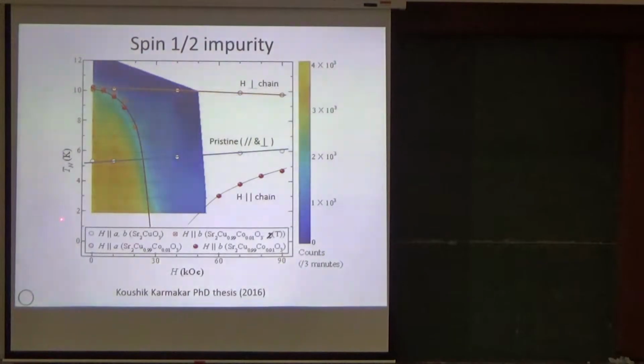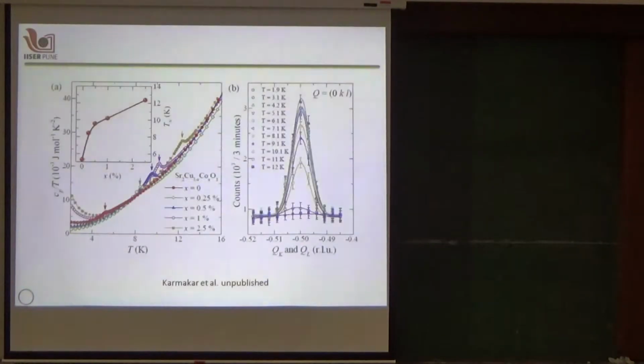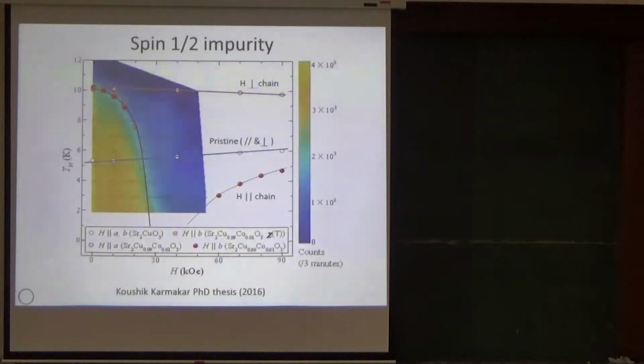So this color plot, contour plot that you see is actually from the neutron data. So the neutron measurements were done down to this temperature. So what is it in neutron? It is probably the intensity of the magnetic reflection, I mean this peak which I showed you here. So neutron seems to be catching the line, but bulk measurements do not. Is it a fair statement?